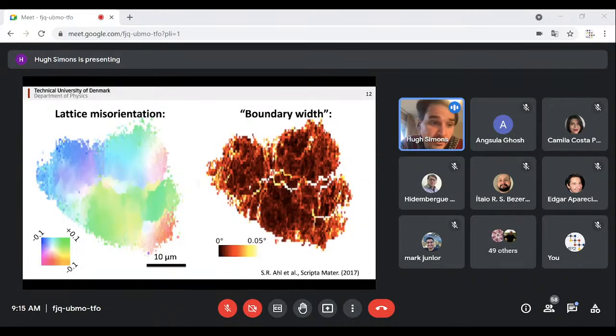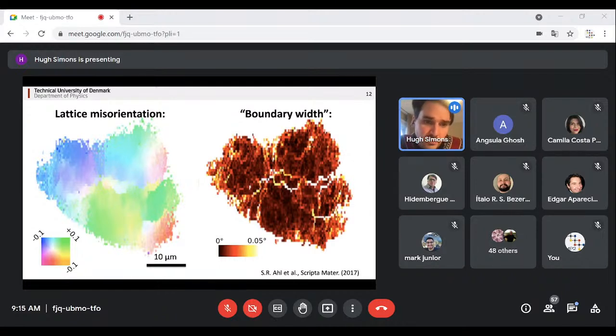What you can see here on the left is an image of the lattice orientation. And on the right, you can see the uncertainty in this misorientation, which corresponds to where the boundaries should be. And what you can see is there are basically some subgrains. So you have different regions that have different average misorientation, and you see some clear boundaries between them.